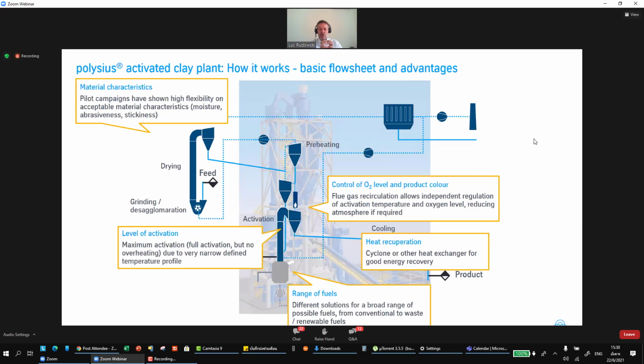But in general, the challenge is to use clay that are available in cement plant deposits where the kaolinite content is just good enough with high iron content, and then the necessity to get gray color, and this is the challenge. So basically the pre-treatment is hammer mill and flash drying, then a preheating stage and calcining, and a color control system in order to turn this reddish color that is created by clay during the activation stage in the calcining process down to a gray color in the reducing atmosphere, and then the heat recuperation is done in a flash cooling system with cyclones.